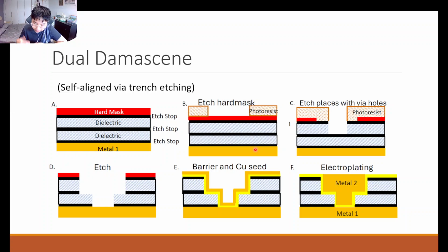Because if you think about it, electroplating requires a conductive electrode to be plated. So you need to have a seed layer to make sure the electrode is conductive. But not only that, it's also to ensure that deposition can occur more uniformly to achieve grain size control and things like that. So eventually, your metal is electroplated into your via and your trench, and eventually the surface is also planarized through a chemical mechanical polishing step.